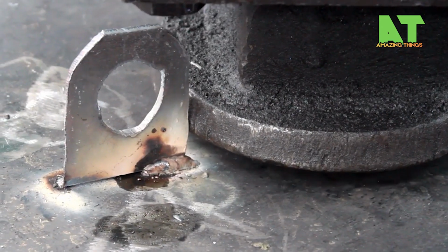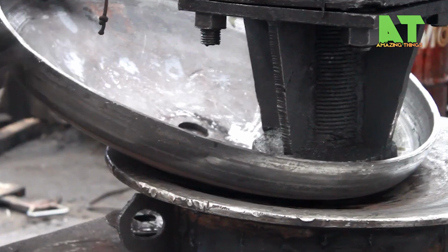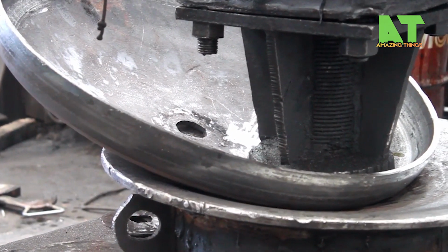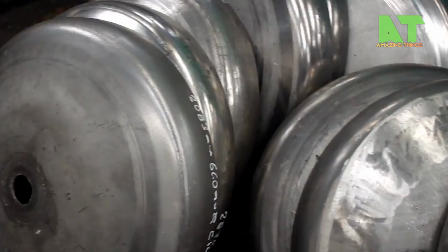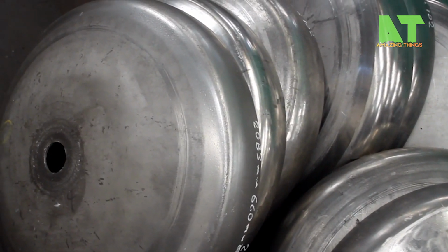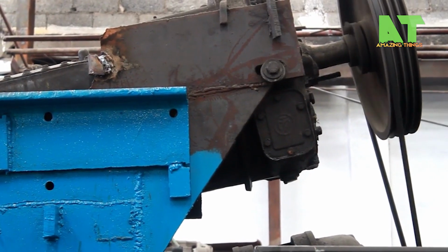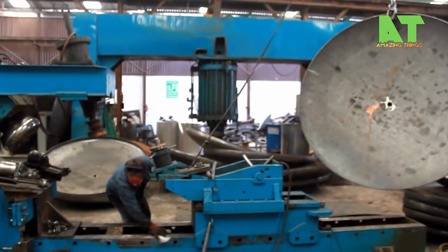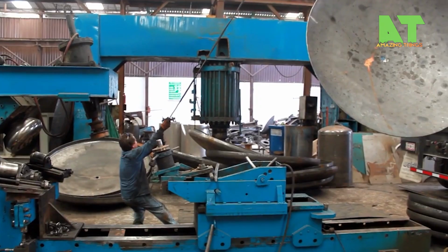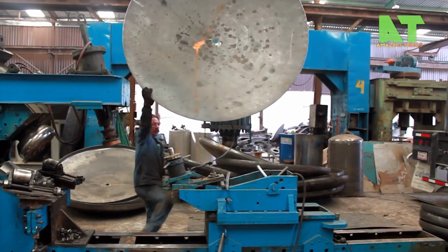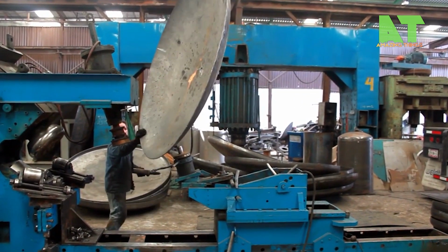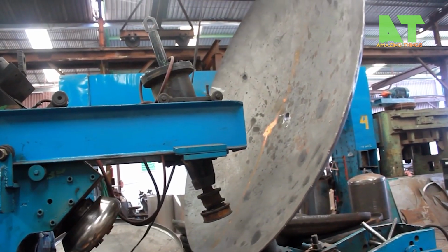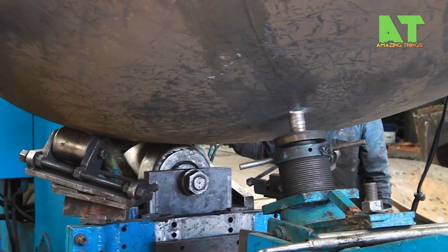For dome shapes specifically, the metal undergoes both radial tension and circumferential compression as it's drawn, a complex stress state that demands careful control of material thickness, lubrication, punch radius, die radius, and drawing speed. After the draw, the part may go through additional forming, trimming, or heat treatment steps. But that single hydraulic press stroke, turning a flat blank into a perfect dome, is where the real transformation happens.